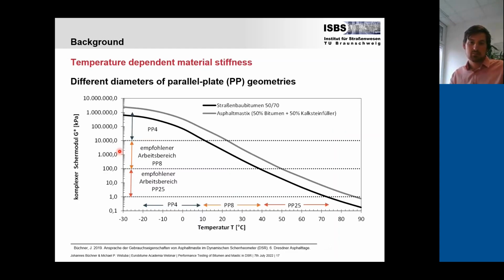When looking at the difference between binder and mastic, this is what I show here. You can see the complex shear modulus on the y-axis and the temperature on the x-axis. I just demonstrated here the behavior of the binder and the change in stiffness with temperature. We are here at 1 gigapascal at -30, so very stiff material behavior, going down to 0.1 kilopascal at very high temperatures. So you see the very extreme temperature dependent behavior. And we also see the same behavior for an asphalt mastic, which is just a mixture of 50% of the same binder, 50-70, and 50% of limestone filler.